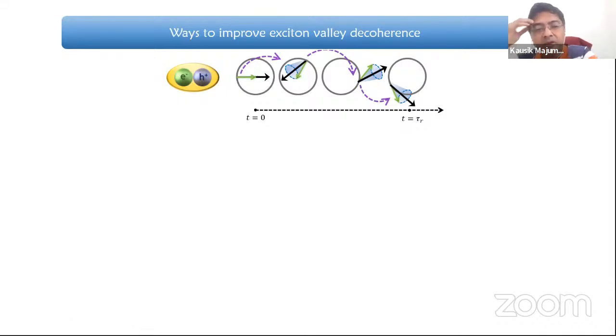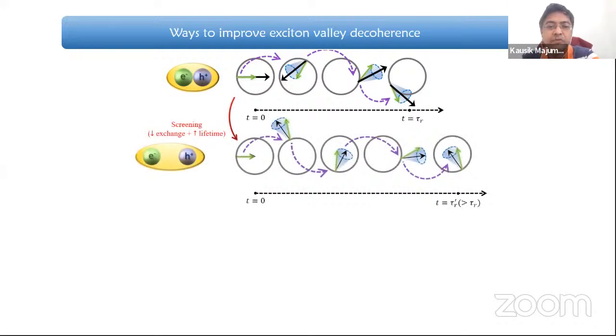So now the question is, how can you improve this situation? The first thing that you can do is screen through environmental engineering. So let's say what we do in this work is encapsulate with graphene. Because of that screening, the electron and hole are sort of separated apart, and so there is less wave function overlap between the electron and hole. And so the exchange interaction goes down. And because the exchange interaction is going down, you should expect that this kind of precession is happening at a slower rate, and you improve your valley coherence.